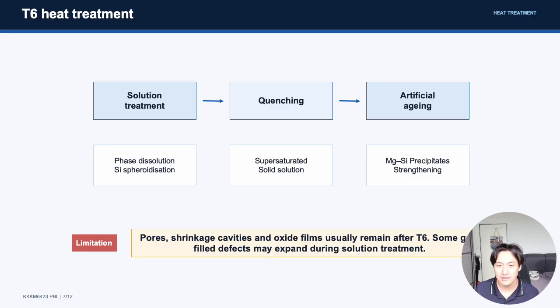The T6 has three main stages. A solution treatment dissolves soluble phases and modifies eutectic silicon. Quenching retains a supersaturated solid solution. Artificial aging forms fine Mg2Si precipitates, which increases the resistance to dislocation motion. This explains the improvements in strength and hardness, but the pores and oxide films are not removed by T6. Some gas-filled defects may even enlarge during solution treatment, so testing quality remains essential.